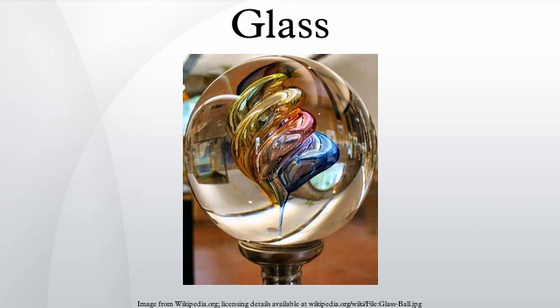The negative thermal expansion coefficient of the crystalline ceramic phase can be balanced with the positive CTE of the glassy phase. At a certain point, the glass ceramic has a net CTE near zero. This type of glass ceramic exhibits excellent mechanical properties and can sustain repeated and quick temperature changes up to 1000 degrees Celsius. Structure. As in other amorphous solids, the atomic structure of a glass lacks any long-range translational periodicity.